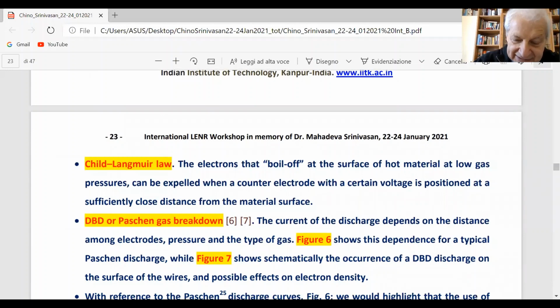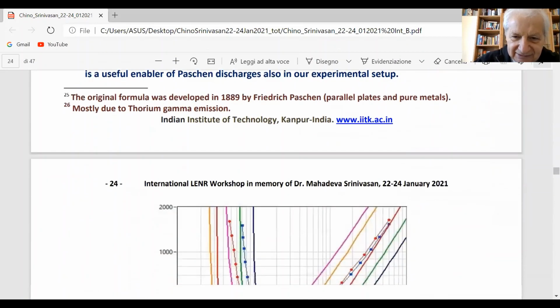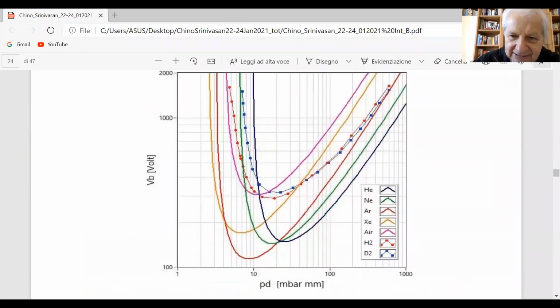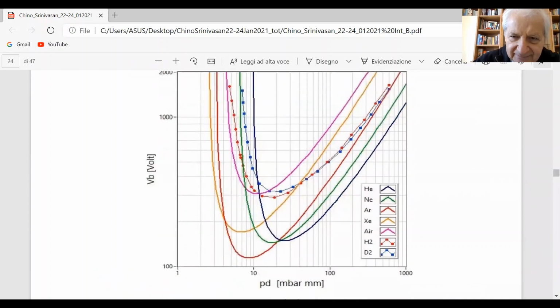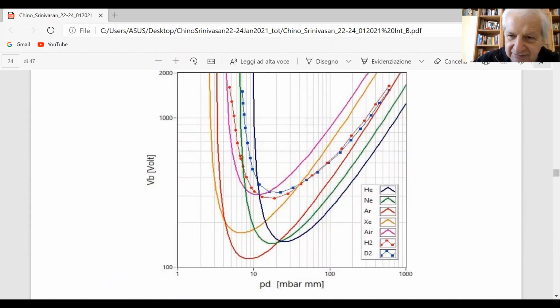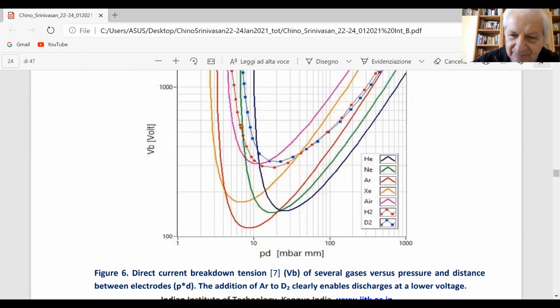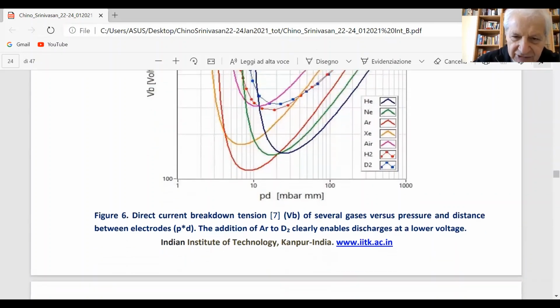And we need the discharge of the gas. So there is the usual Paschen curve. In the case of hydrogen or deuterium, the curve is made with dots in this figure. We have to have a larger voltage to have some pressure inside. So there is a compromise between the pressure to have a discharge and the total voltage of the system. For practical aspects, we want to limit to 1000 volts. So we mix into the hydrogen or deuterium, argon, which has a better performance for discharge, meaning at a lower voltage.